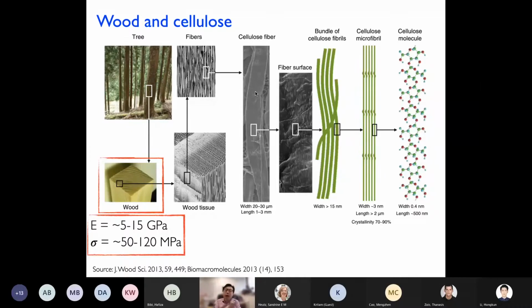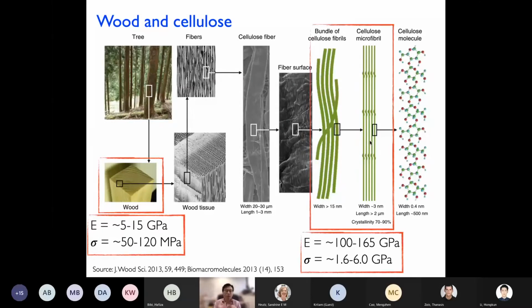Now, this cellulose fiber is actually not the ultimate ending length scale. You can refine it further down to the bundles of cellulose fibrils, which you can then refine further to the elementary building block, the cellulose microfibrils. And if you refine cellulose microfibrils further, if possible, you get to the cellulose molecule. Now we'll stop at the cellulose microfibril scale. In that bundle of cellulose fibrils or cellulose microfibril, the width is somewhere between 15 nanometers and 3 nanometers, depending on how you refine them. The Young's modulus, or the tensile modulus, in this case E, is between 100 and 165 gigapascal, so that is stiffer than glass fibers. And bearing in mind, these are 3 nanometer, 15 nanometer fibers.